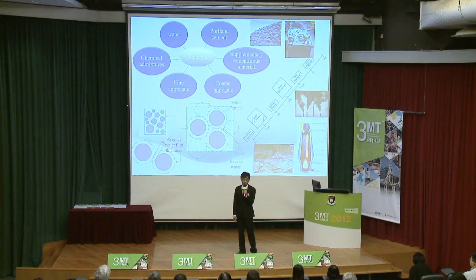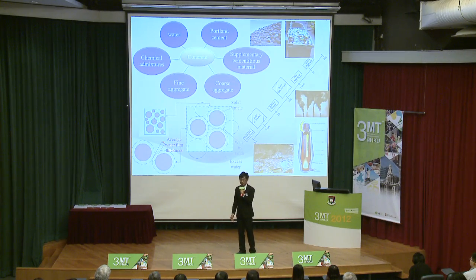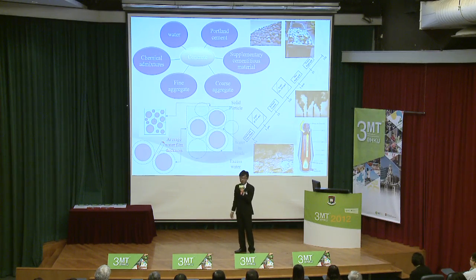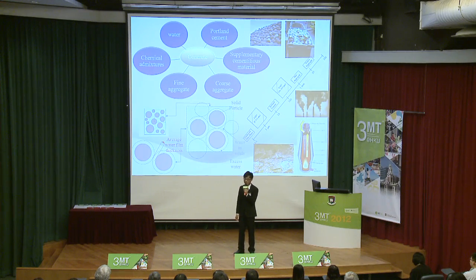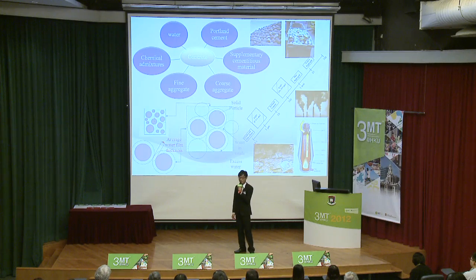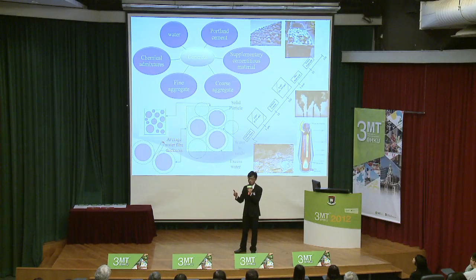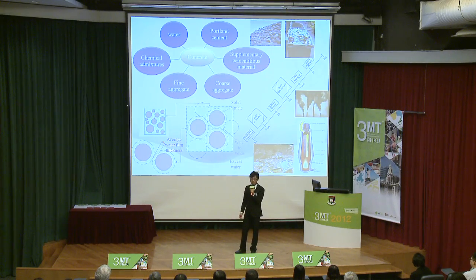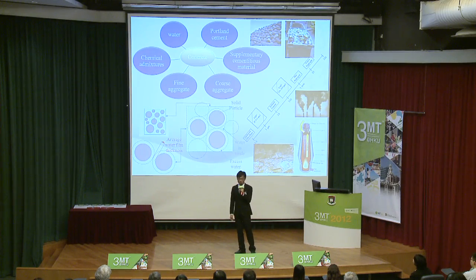Our research team proposed a new mix design method considering fresh concrete as a water-solid mixture, and combining the effects of water content, particle packing density, and solid surface area together into one parameter — water-film thickness — which has now been demonstrated as a governing factor in mix design.